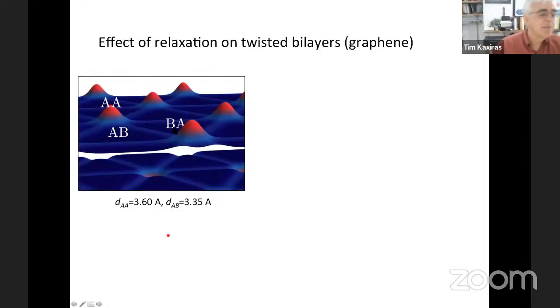So this is essentially the picture that comes out from the atomic relaxation. You see two graphene layers here. This is the top layer, this is the bottom layer. And the color scheme tries to capture the relaxation. The AB and BA regions are closer to each other. There's a relaxation on the vertical axis as well as in-plane relaxation. So these are the two regions closest to each other, and the AA regions repel each other, and the distance of the atoms in the AA regions is farther apart than the normal graphene interlayer spacing. The distance between layers in AB regions is 3.35, in AA regions is 3.60. So that's about a 10% increase, which is quite significant.